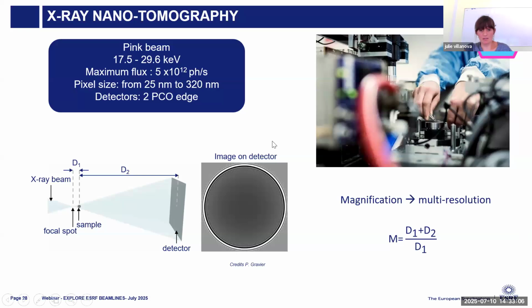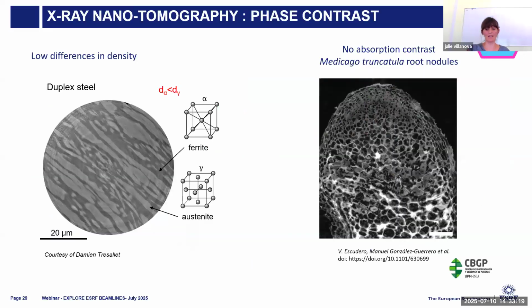As you can see on this image, we see large fringes at the border of the sample. This is because we are not working with absorption contrast tomography, but with phase contrast tomography. And why this? Because it allows us to image non-absorbing material, for example all the biological samples, but also in material science, polymers, or lighter materials. And also because we can look at the difference between phases that have low differences in density, as for example here on the left, on the duplex steel, where we are able to discriminate ferrite from austenite.